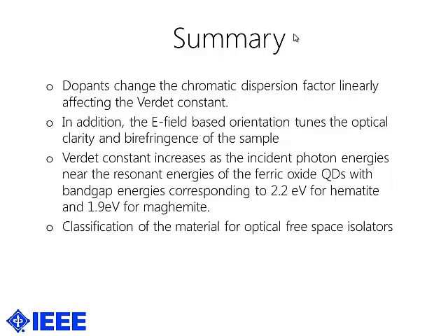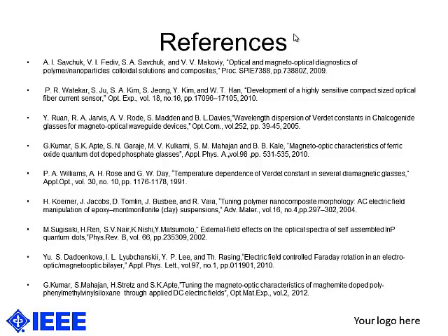Now, if somebody is curious as to how it is that I could call them quantum dots, they have a Bohr radius of about 24 nanometers. And if you look at the sizes of the nanoparticles that I showed before, they were in the range of 50 to 60 nanometers. It's highly possible that they showed a weak quantum confinement effect. And we did have particles smaller than 24 nanometers that we noted in the study, which is one of the main reasons that we are stating this. And the main purpose was classification of this material for optical free space isolators, which we were able to find out as a part of this fundamental study. And that's it.